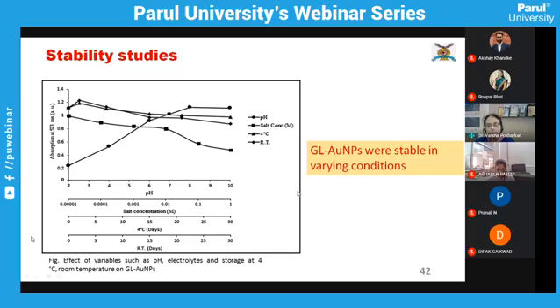The stability studies were done for these glycyrrhizin reduced gold nanoparticles in different pH conditions varying from 2 to 10. We keep the gold sol in different pH for a considerable amount of time, and then record its absorption band, the surface plasmon band. You can see that in different pH conditions there is no change in the surface plasmon band, which indicated its stability in the pH range of 2 to 10. Also, we looked at its stability in different electrolytes, sodium chloride solutions of different molar strength, where again it was found to be pretty stable, and at a temperature of 4 degrees Celsius for 1 month and at room temperature for 4 months, the particles did not show any aggregation.